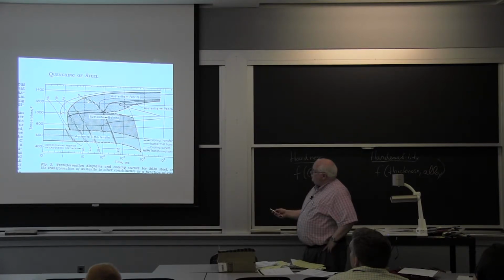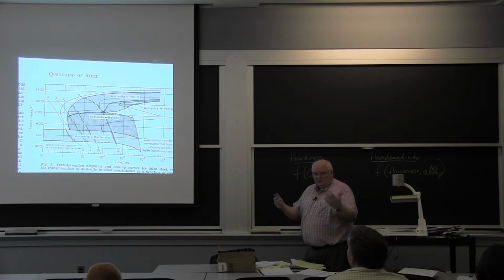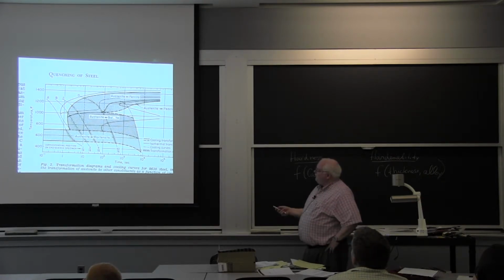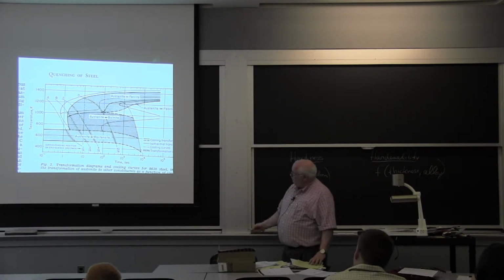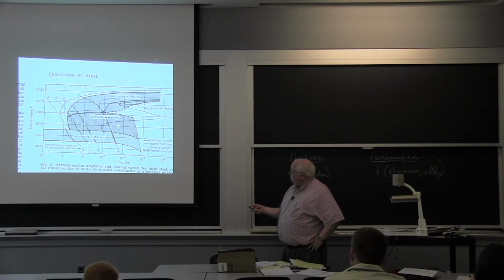If I cool at a slow rate like D here from a higher temperature, I'll go through the transformation to ferrite. If I have something in this region, I can transform to bainite, which is this sort of region that the old people before the 20th century didn't know about. Edgar Bain discovered bainite when he was doing tests where you quench into liquid lead and hold it at temperature. So he was able to come down, transform. And we actually do those types of heat treatments now when money's not an object. Okay. It's expensive to do that, but we can do it.